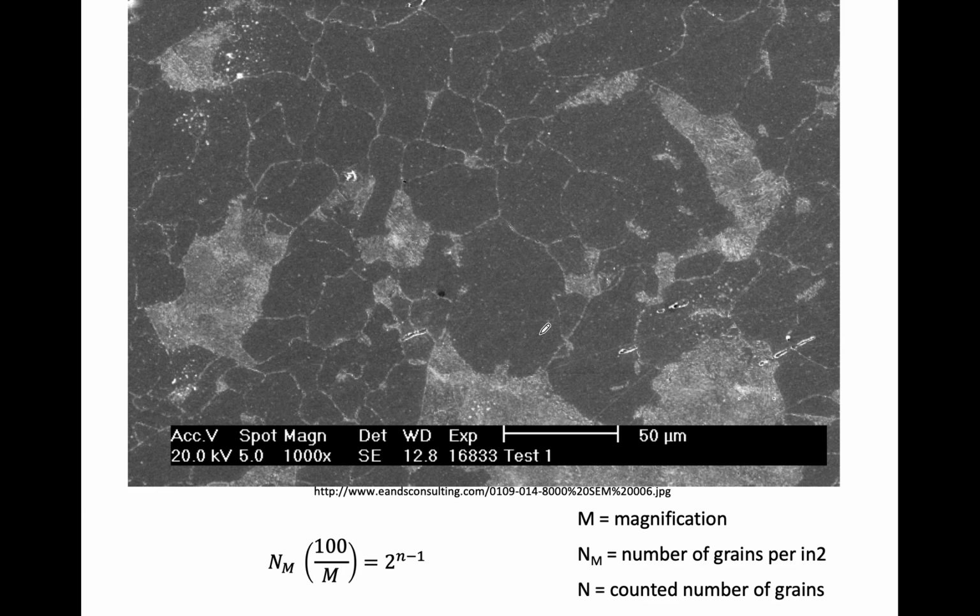So here's another opportunity for you to practice doing the best you can, since I didn't tell you what material this is. One thing I'll say: things that you see like this are most likely dust or dirt on the image, so you can ignore that in your counting. This would be 1 grain here. This is going to be a grain. This is going to be a grain. But do not count these little things as grains. And if you see something that's a tough one, that's a judgment call, whether this is 1 grain here or 2, and whether this connection here is not clearly visible. That's a judgment call. And the reality is that being off by 4 or 5 grains in something with this many grains is not going to make a significant impact on the ASTM grain number.